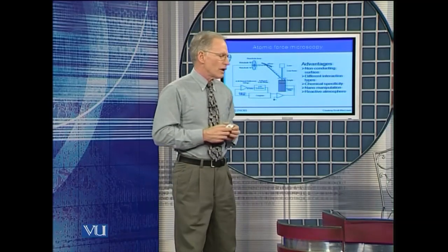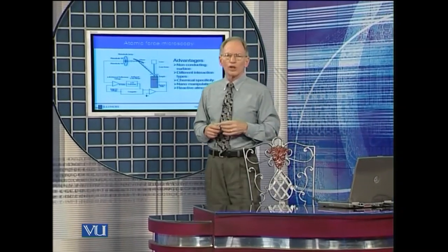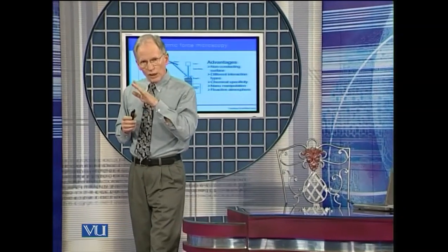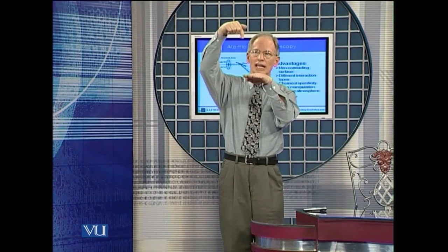Okay, let me talk about another technique which gives me insights into atomic processes, and that's atomic force microscopy. When I talked about scanning tunneling microscopy, I said I have a tip and a surface and charge flowing from one to the other, current. That means that the tip and the surface have to be either metallic or semiconductors. If one is an insulator, then I cannot flow charge from here to there and then to ground because I would simply build up charge. So I do not get a map of the surface with scanning tunneling microscopy. And that's just not acceptable.